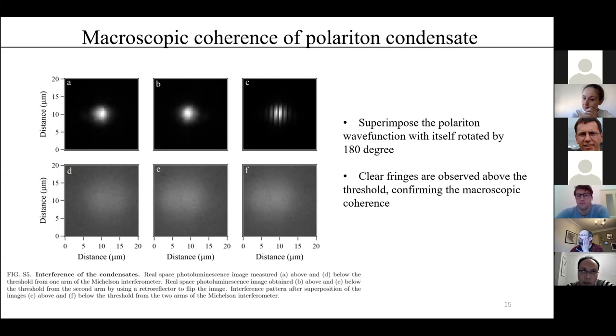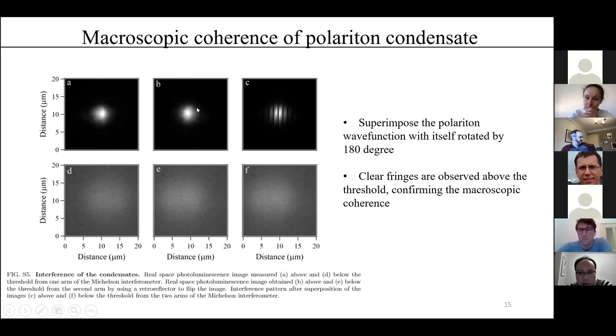So the laser spot of the femtosecond laser is very large. The size of the perovskite is because when we transfer, there are many perovskite microplates. This one is around 50 micrometers. But it looks like really it's lasing. I mean, the condensed polariton looks localized in a small region around 5 micrometers. So in other areas we do not see the signal from the microcavity above the threshold.